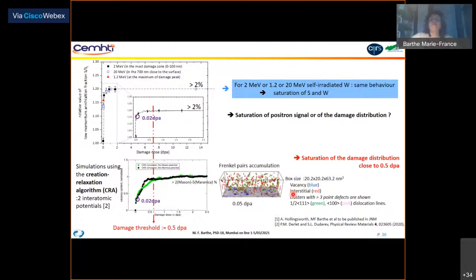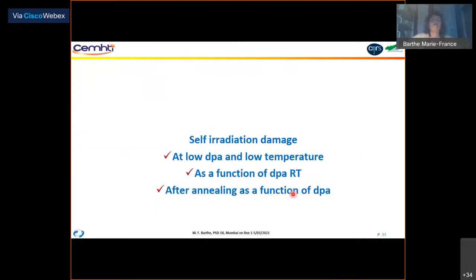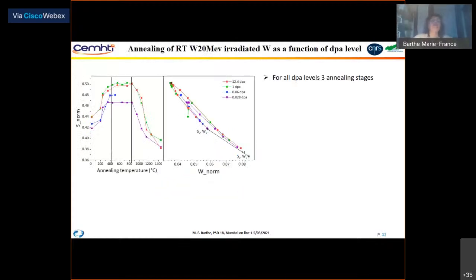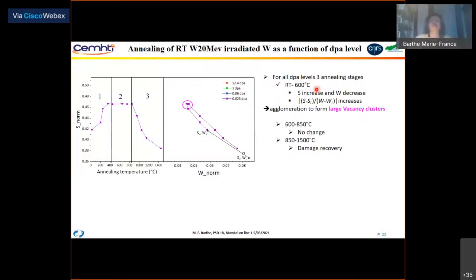We also check if this positron signal saturation exists by annealing the samples irradiated at different dPa level. And you can see that from 0.03 dPa to 12 dPa, there is exactly the same behavior of the S as a function of annealing temperature. And there are 3 annealing stages. The first between room temperature and 600 degrees C, where we can see the formation of large vacancy clusters. And after that, we have a stage between 600 and 850, where nothing happens. And then the S decreases, corresponding to the damage recovery.